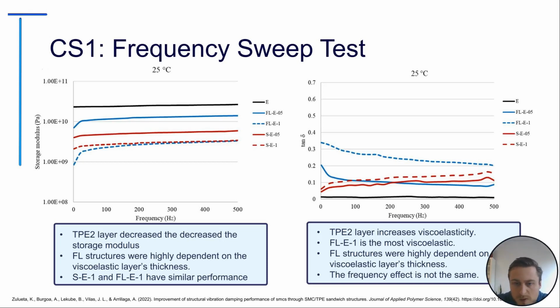So the frequency sweeps at room temperature showed that the viscoelastic layer decreased the storage modulus, and that the free layer, or FL, structures were highly dependent on the viscoelastic layer's thickness. They also saw too that the sandwich and free layer with a 1 millimeter thickness viscoelastic core had similar performance.